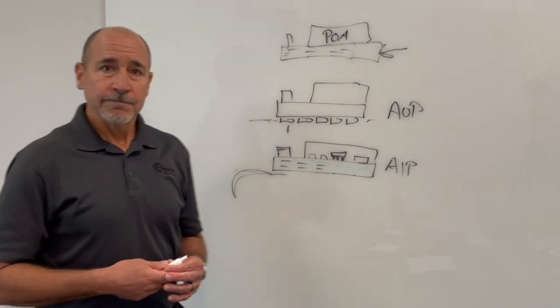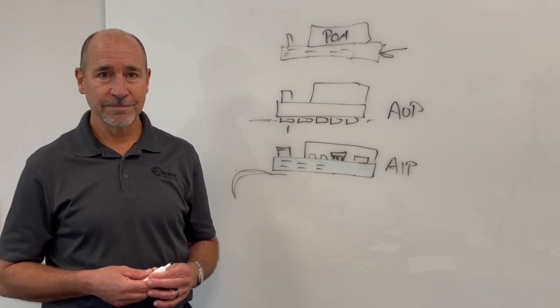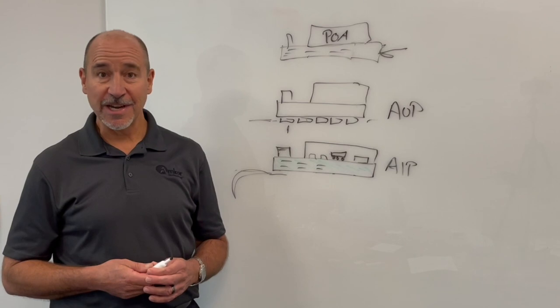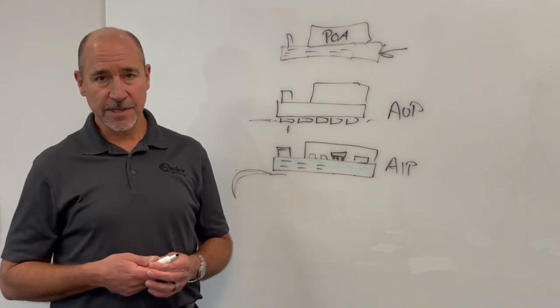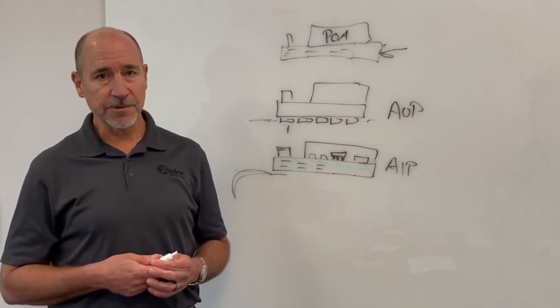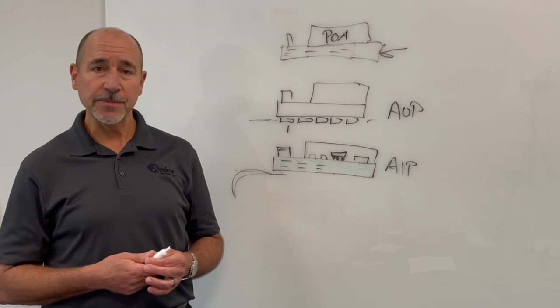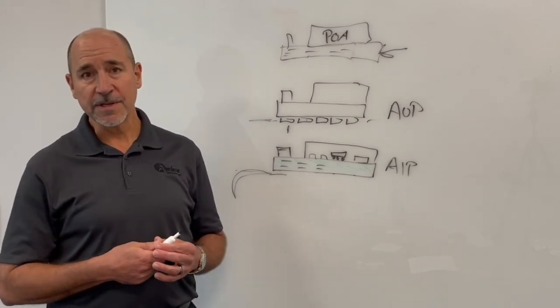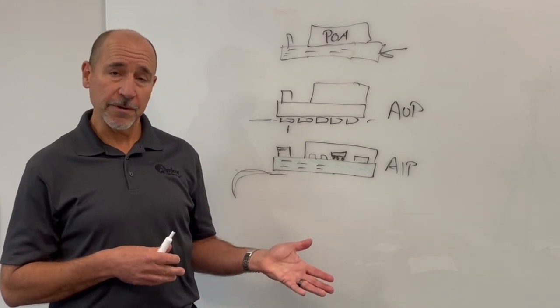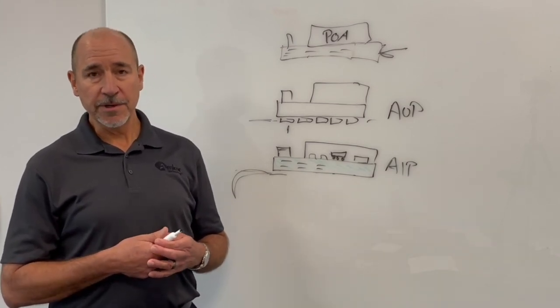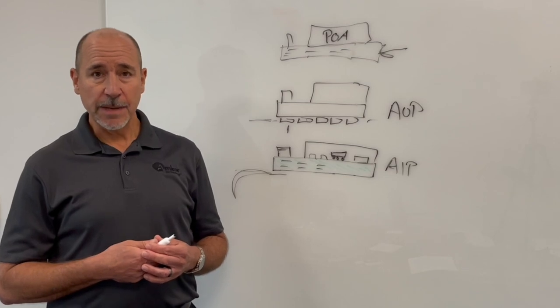We're also starting to hear about some glass substrates, which are interesting. We've been talking about glass substrates for probably almost 15 years now. Why now, what does it bring to the table, and what are the problems? Good question. Yes, glass is getting a lot of attention, and has for probably the past 8 to 10 years, even at our industry conferences, because clearly it has some of the best dielectric constant and return loss characteristics of any material other than diamond, for instance. So it's very, very exciting, because the glass industry has really put a lot of emphasis on not just providing standard glass that we see in our homes, but glass that has unique transmissibility characteristics, unique CTE characteristics that can help them to use as wafer carriers for our wafer 2.5D carrier industry, also now for applications as an alternative for BT core or other type of cores that are being considered. So glass, it's cost effective.